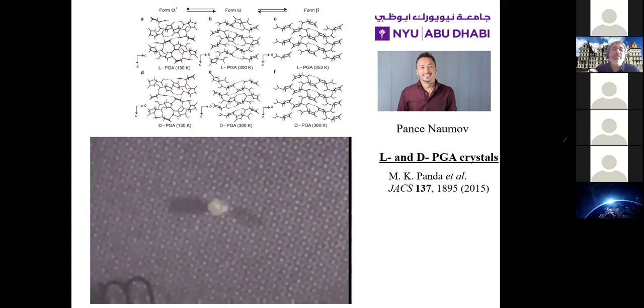Well, what's happening in this movie that you're seeing is that there's a hydrogen bond network in this crystal, which switches from, let's say, a short hydrogen bond in one place to a long hydrogen bond in the other. These switch places. And it's sort of like snapping a rubber band. When that happens, a lot of energy is actually released, and it releases along one direction or one of several directions, which cause these things to jump off the plate.